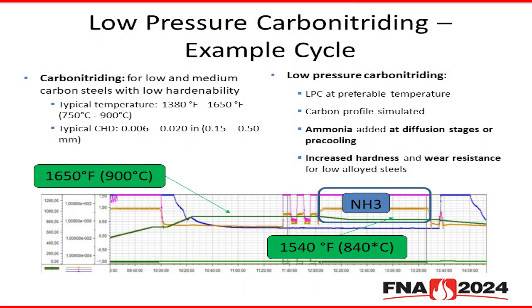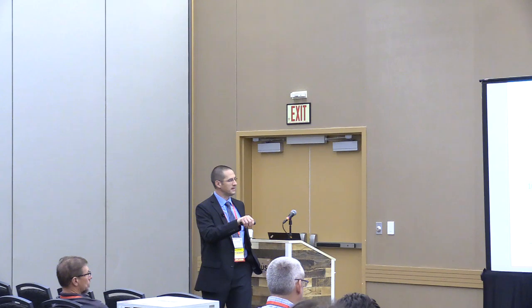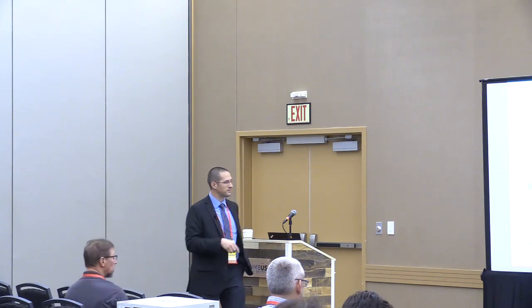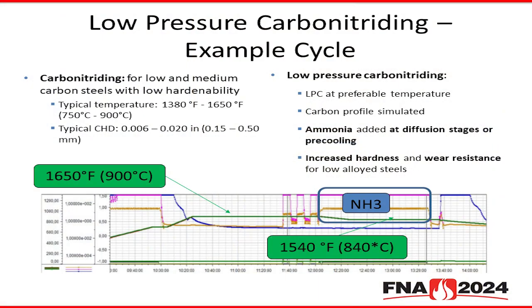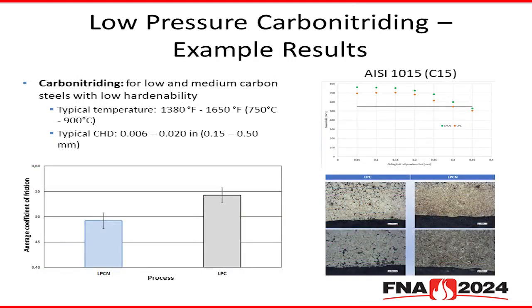And as you see here, this is a process trend, if you will, from the simulated cycle. Here you'll see the main heating section, and then the section where we're introducing ammonia during the boost and diffuse portions of the process. Typically, for this type of application, we want the nitrogen concentration to be somewhere around 0.3 to 0.4% by volume. As a result, using, like I say, a low hardenability steel, such as 1015,